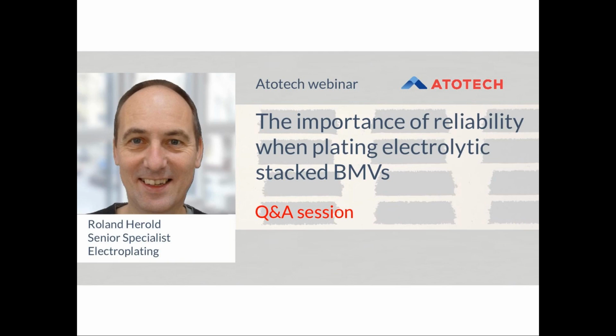When you apply now a very strong reverse pulse, on the other hand, you clean the surface by this reverse pulse. And cleaning means also during nucleation of the plating process, you have adsorption of additives and you etch them away, and so yes, you can reduce the adsorption of plating additives by stronger reverse pulses, by stronger reverse charges, but the risk of course will increase to damage the electroless copper layer.